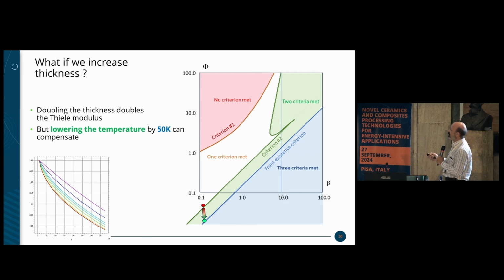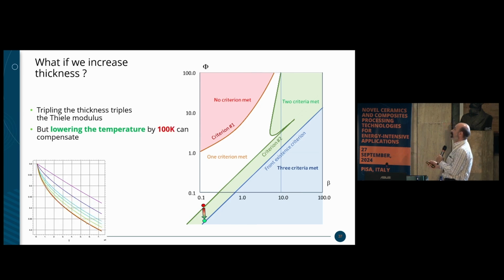And the simplest way of doing that is lowering the temperature. In that case, by 50 Kelvin, you lower the temperature and you can compensate. If you triple the thickness, then you have to lower even more the temperature. The problem is that, of course, things are getting slower because, well, 100 Kelvin means like 5 times slower.